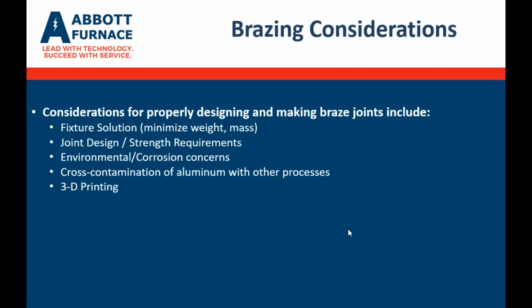Even though the fixture may do a very good job of stabilizing all of the components together, in some cases they're quite heavy, and many times we've seen them even many times higher in weight than the actual aluminum heat exchanger itself. I know there are some applications we're looking at now where, just for example, the aluminum may weigh 1 pound, but the fixture may weigh 10 pounds. So when you look at it from a thermal input standpoint, that is a lot of energy, a lot of electric that is required to heat that fixture over and over again.